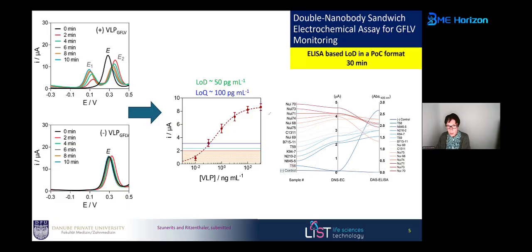So for this, you can now make calibration curves like you see here. You get currently a limit of detection of around 50 picogram per milliliter of these proteins around the viruses, with a limit of quantification of 100 picogram per milliliter. So what we did was to see if this detection limit is more or less good enough for real sampling.